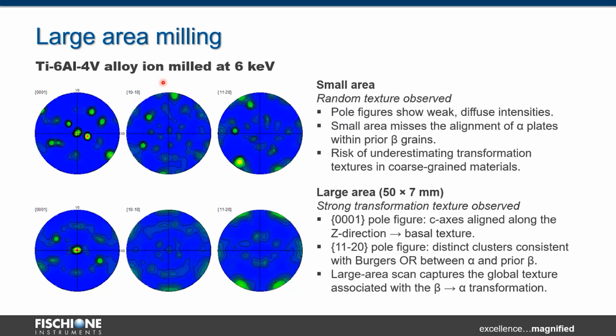Here, another example of the importance of large area is that the large area shows a strong basal and 1120 texture, as you can see here, which are the signature of Burgers orientation relationships from beta to alpha transformation. By contrast, the texture obtained from the small area appears random and fails to capture global texture. So 50 millimeters sounds big, but still you will not know the true texture of your material in that case. So this highlights why large area sample preparation is critical for accurate microstructure analysis.